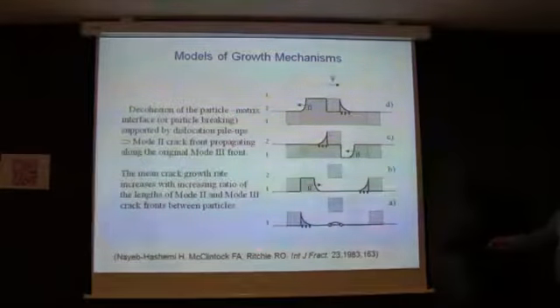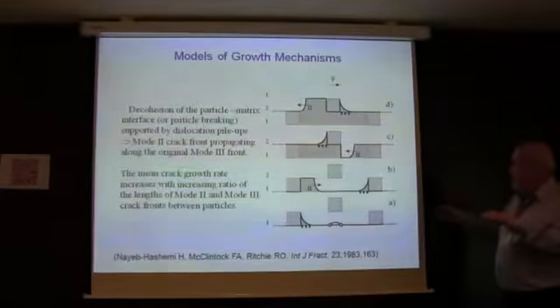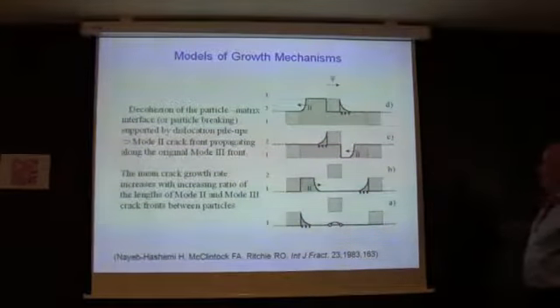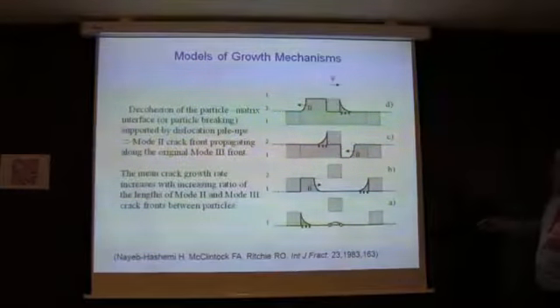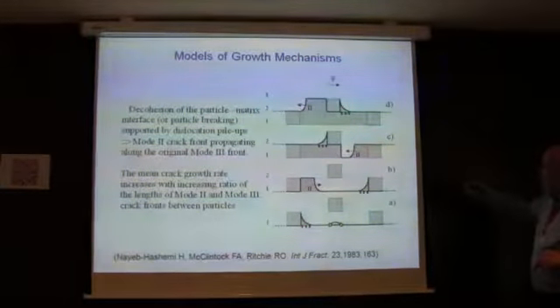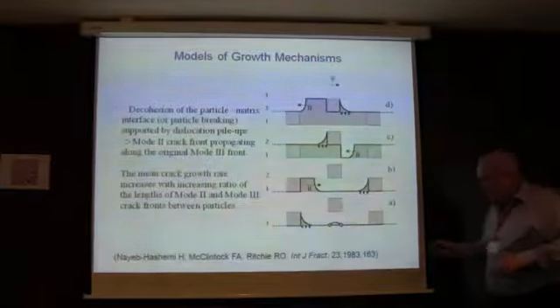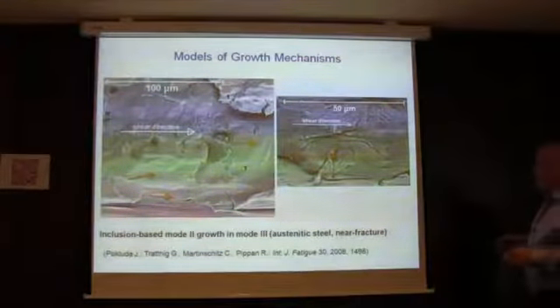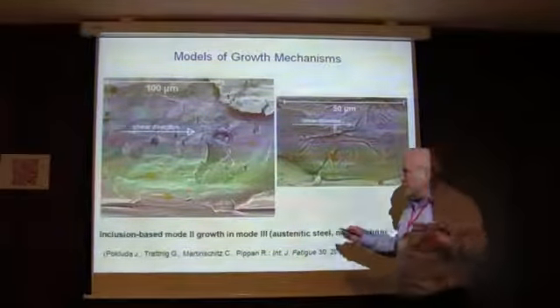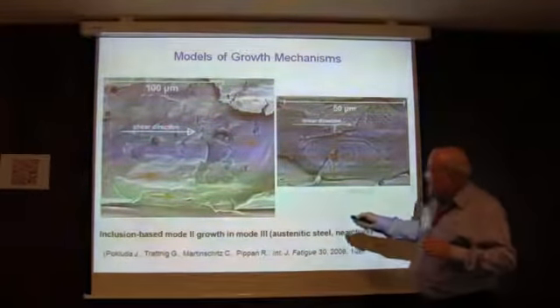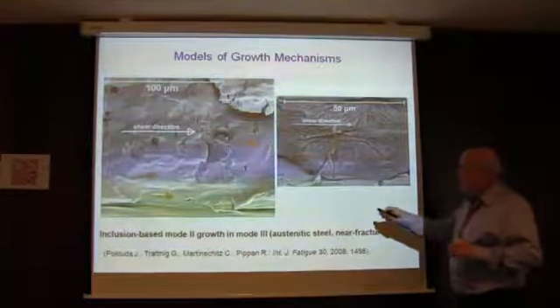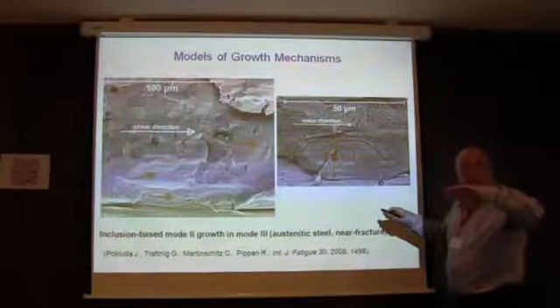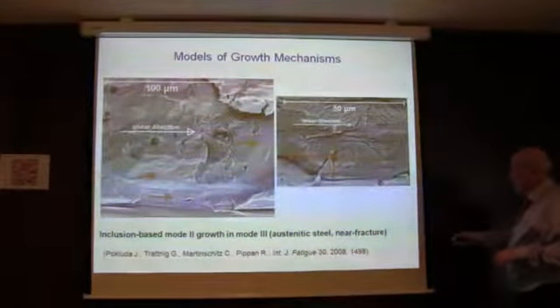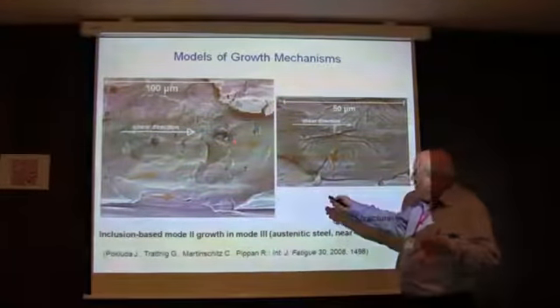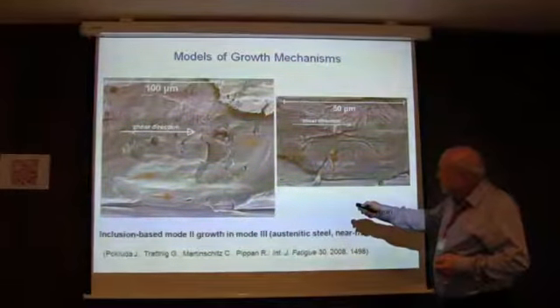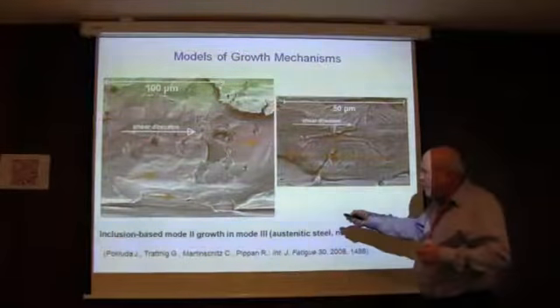There is another model by McClintock and Ritchie, that shows that if you have really a straight crack front, with no need for roughness, you can propagate mode 3 also by mode 2 if you have particles and the decohesion of particles, and the mode 2 cracks can propagate like this. Okay, this is experimental evidence that if you have particles, inclusions like that, this is a shear direction like this, it's mode 3, but you always have some mode 1, so you can get the striations. It's austenitic steel near the fracture region, so that's high applied stress, so you can see the striations. And you can see that the crack propagates like this. So this is mode 2 propagation along the crack front.